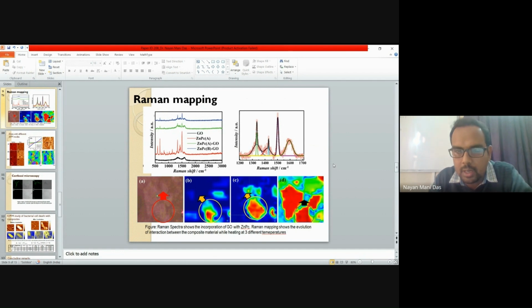We had to convolute this composite peak in order to show the different interactions between this composite material. We also did the Raman mapping for our composite material, and from here we see that when it is heated, the interactions are proper. So the graphene oxide and the different parts of the composite material are aroused. In case of non-heating, where this ZnPc is in J aggregate form, their interactions are very less. So from this characterization also, we could see that the interactions between the two molecules were very prominent.